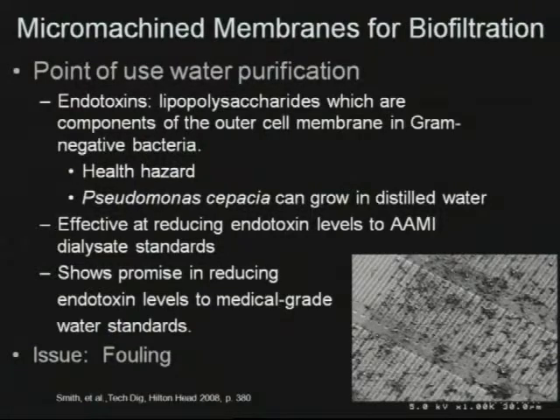We find these things are excellent for use as a filter. We haven't made the bioartificial organs yet, but we've tested them for water filtration applications, and we find that they are actually excellent at reducing endotoxin levels, which is kind of a nasty thing that's found in many water sources, down to medical grade standards. And we think that there's a lot of opportunities here in developing water filtration cartridges out of these nanoporous membranes. One issue with membranes, however, is fouling. When a membrane fouls, it will no longer filter. And so we're interested in coming up with surfaces that are anti-fouling.